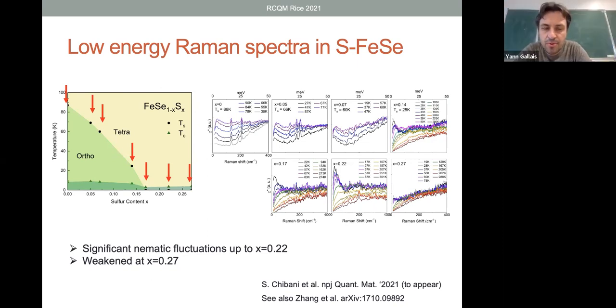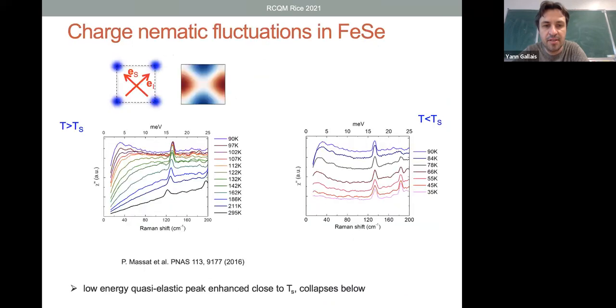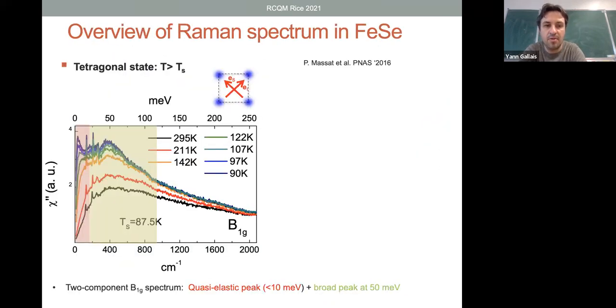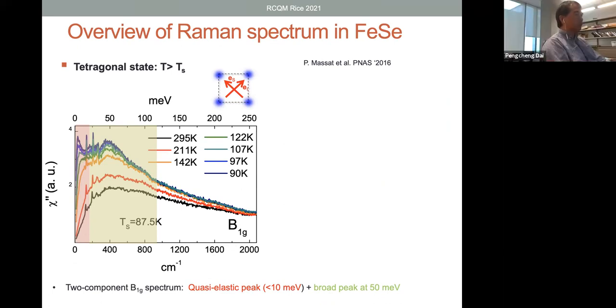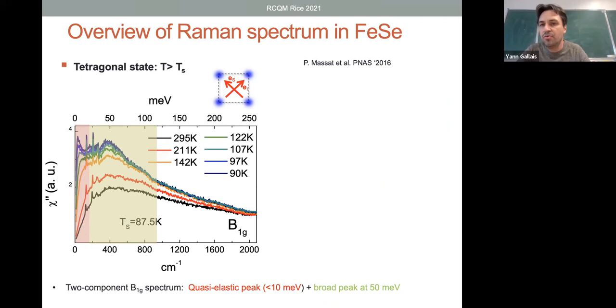For this quasi-elastic peak that I'm focusing on in iron selenide, the range of energy where it's spread is not so different between iron selenide and barium 122 systems. So it's essentially below 20 meV. In all, it's not terribly system dependent. The one that is very specific to iron selenide is this broader feature that I alluded to before, this broad peak at 50 meV. This is very special to iron selenide. But the low energy part is similar, always below 20 meV, and this is sort of universal if you want.